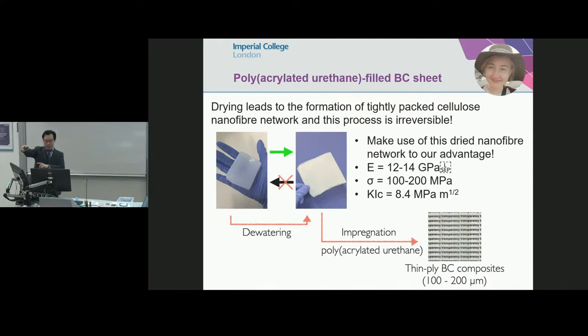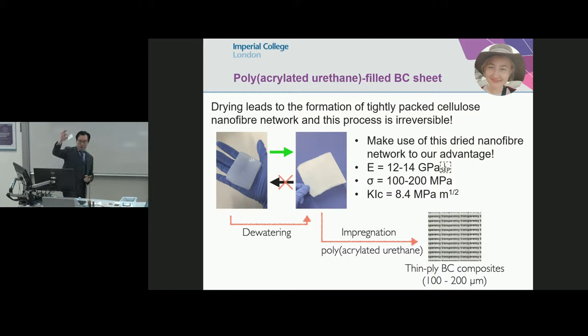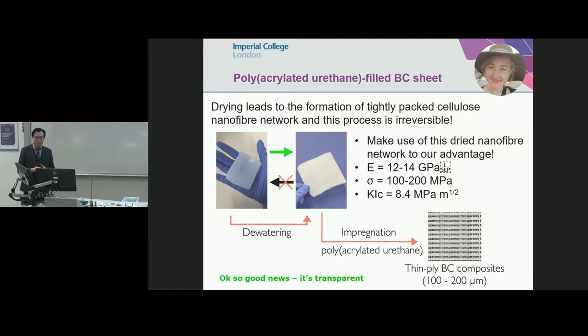So this is where Daniela, sitting right at the front here, comes into play. So she decided that she would take that piece of bacterial cellulose pellicle, dewater them, and then impregnate that with a polyacrylated urethane resin. And there is a piece of sample there. It is transparent. If you can't see it, trust me, it's there. It is transparent, so that's great. So we actually get a transparent, thin polymer composite that's starting from this, it turns to a transparent structure. That's great. So we were happy with that.